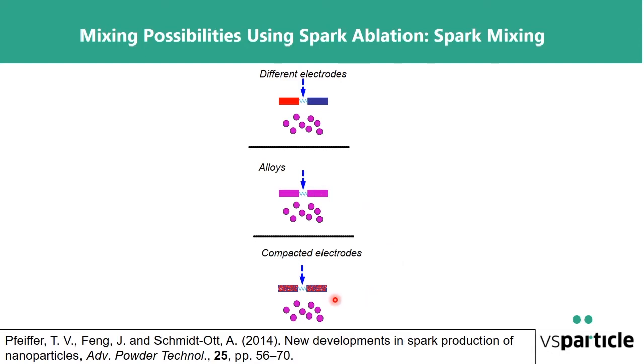Now, what if the alloy does not exist in the macroscopic case? Well, what you can do then is make a powder, mix the powder, and then compact the powder and make electrodes out of this compacted powder. And that way you can then make particles, and in most cases in the nanoparticle state, the alloy will exist.